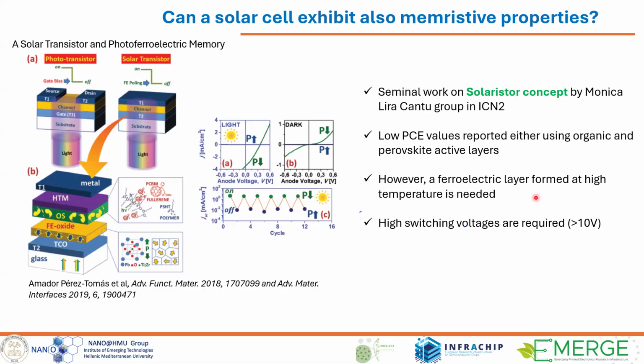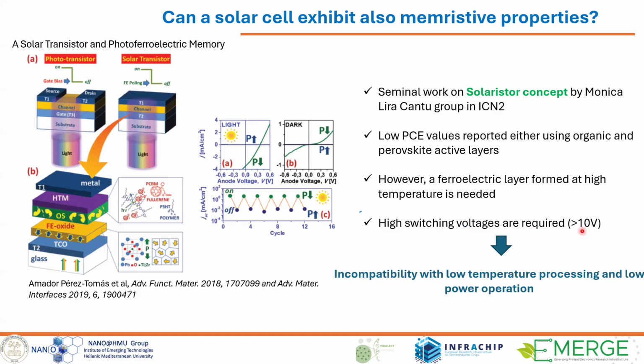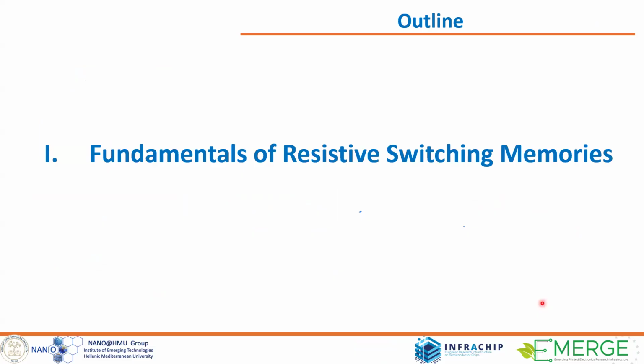However, the ferroelectric material required a very high temperature to form, 500 degrees or more, and the switching voltage for the ferroelectric polarization was more than 10 volts. So these are not compatible with low temperature processing, so flexible substrates, and low power operation. I will show you how we continue this work.